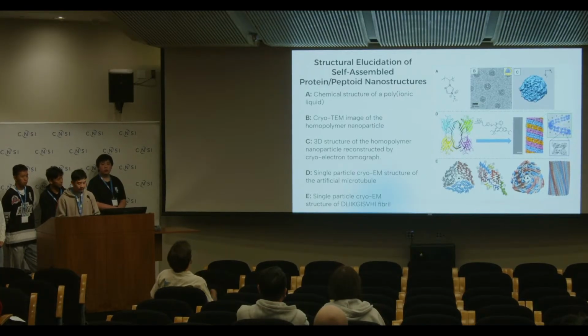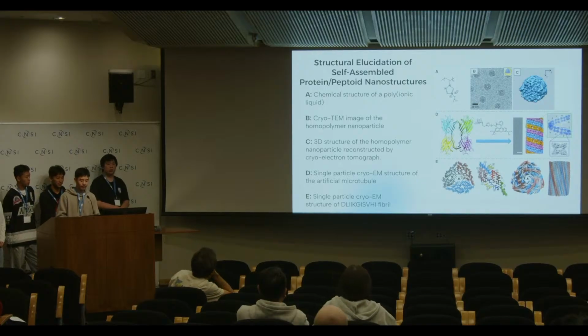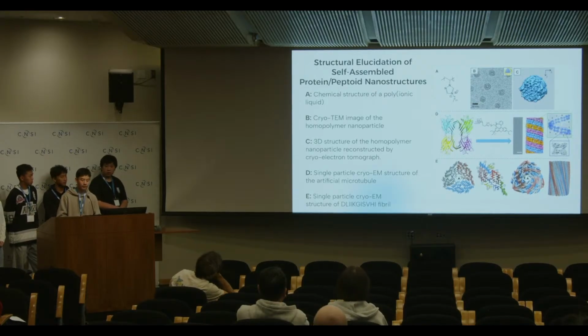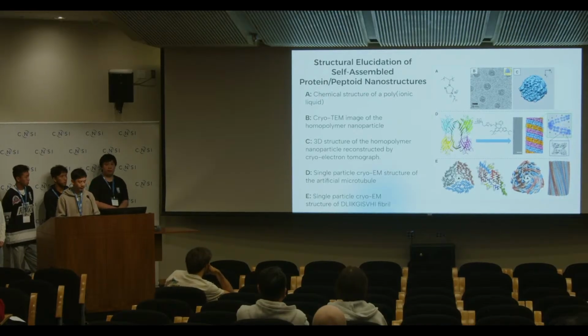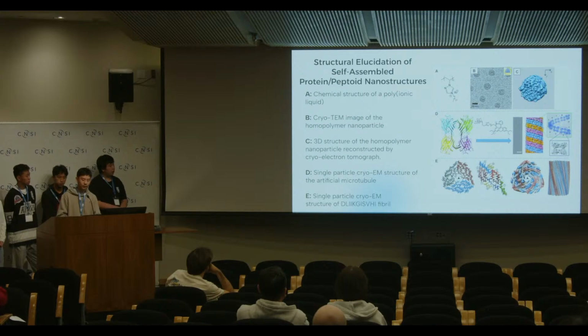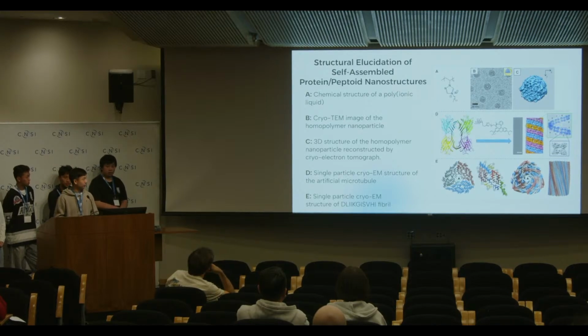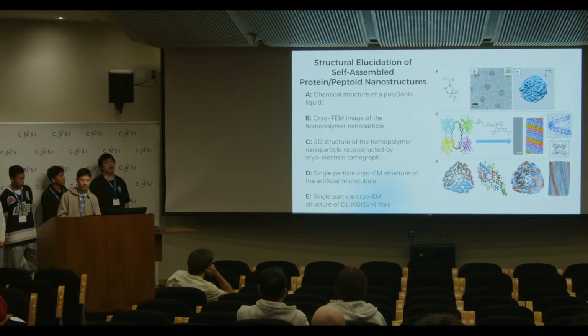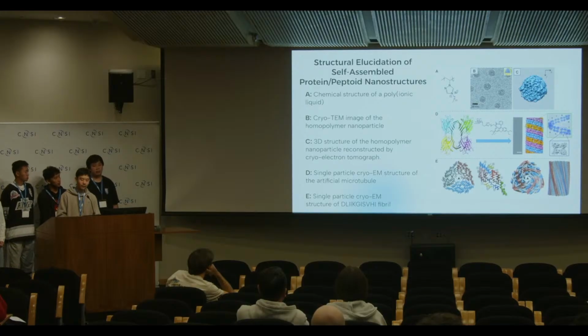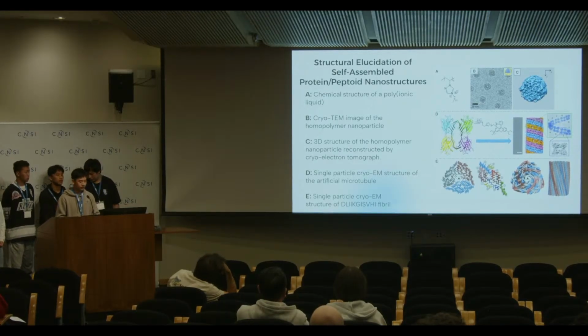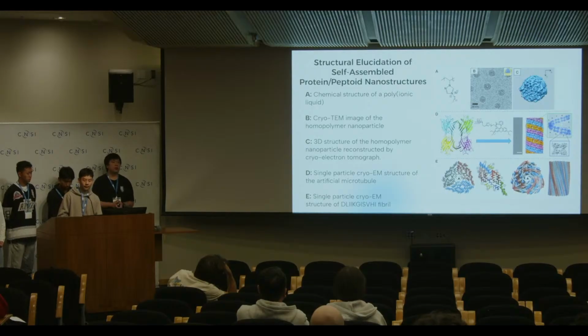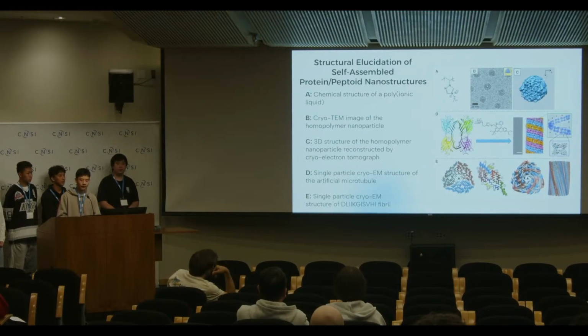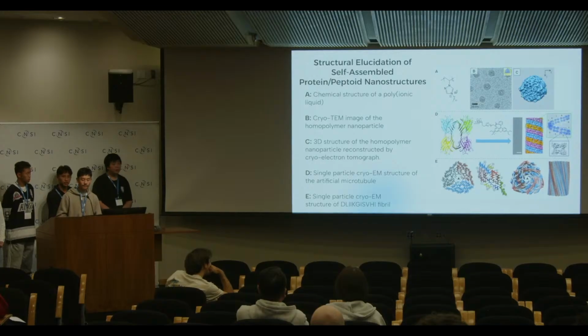In panel A, we see the chemical structure of a polyionic liquid which self-assembles into homopolymer nanoparticles smaller than 50 nanometers. The 2D cryo-TEM image in panel B suggests an onion-like layered internal structure with 5 nanometers of spacing. However, the 3D reconstruction from cryo-electron tomography in panel C reveals a much more complex internal structure, going beyond what can be interpreted from 2D images, and it highlights how tomography adds crucial depth to structure interpretation.